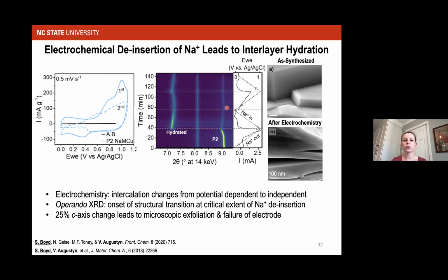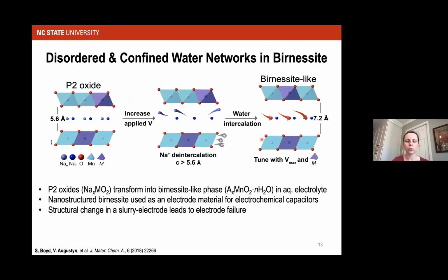So we now understood the mechanism, and this is what it looked like. You take these P2 oxides, and depending on the transition metal layer composition, when you applied a critical voltage to remove sodium from the interlayer, water would come in to take the place of the sodium ions. That leads to a phase transition and electrode failure. So that was kind of disappointing, and it was challenging to have reviewers actually publish this study because it wasn't going to give you a record-breaking performance. It was detailing a degradation mechanism essentially.